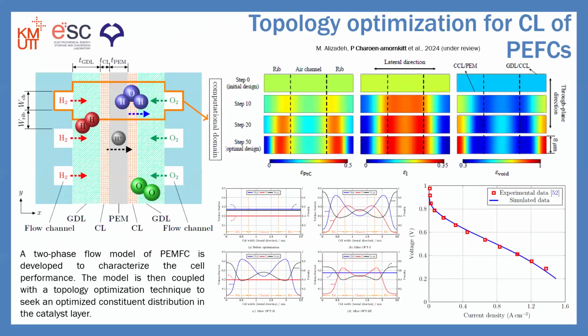In this study, we consider a full cell as seen on the left figure, and the model is well validated with the experimental data from a previous study. After the optimization routine, results indicate that an electrode with a heterogeneous structure can enhance the overall cell performance by balancing various transport and rate processes. The performance enhancement is formulated as a higher voltage at every current density. This optimization problem is constrained in a way that the overall material amount used in the topologically optimized catalyst layer would be equal to that of the reference catalyst layer before the optimization. This is to ensure a fair comparison to answer the question like, if we have a different amount of material, where should we put it so that the system will be more efficient?